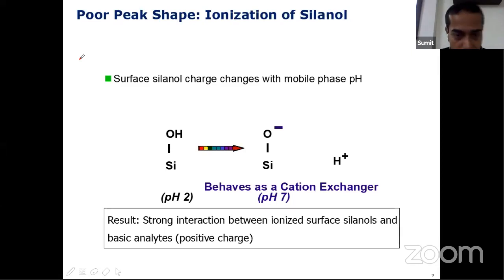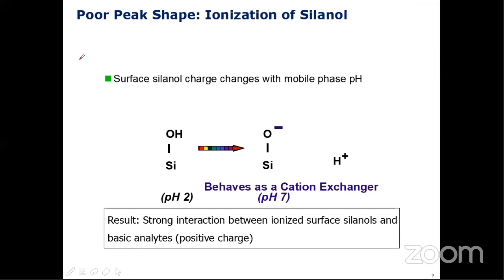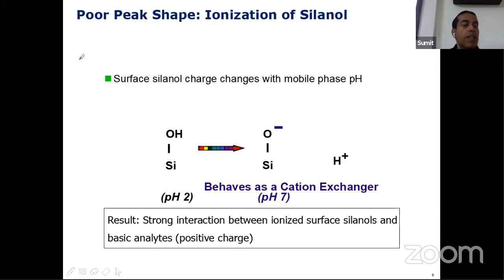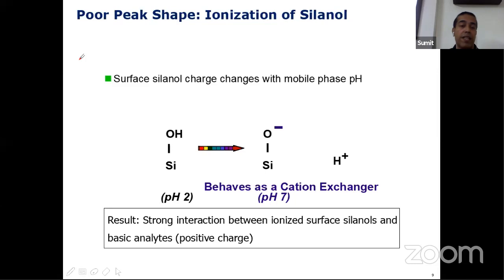As you see from this equation, when we have a pH of two — we are talking about the pH of the mobile phase or the solvent used in HPLC — if our pH is close to two, the silicon hydroxyl group, which is silanol, remains as it is. But if pH typically exceeds three and goes up to pH seven, the silanol group tends to get ionized and forms some negatively charged species. That causes the problem, which we'll see in the next slide.